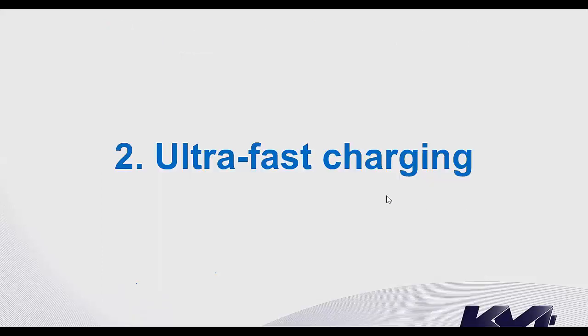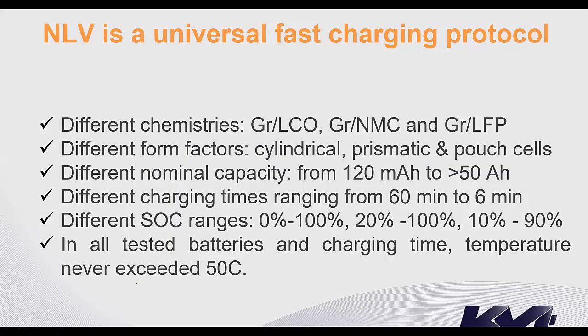So this NLV, what we found is that it applies to any type of battery chemistry: lithium-ion battery with graphite and lithium cobalt oxide, LCO, graphite and NMC, nickel manganese cobalt, and graphite lithium iron phosphate. This is the very famous cathode material. Graphite is always the anode used in lithium-ion batteries, but the cathode materials can be very different. So the different chemistries, different form factors, cylindrical, prismatic, and pouch cells, and also different capacity going from below 1 ampere hour, like here 120 milliampere hours, to more than 50 ampere hours.